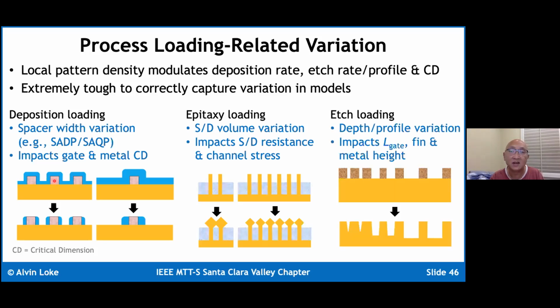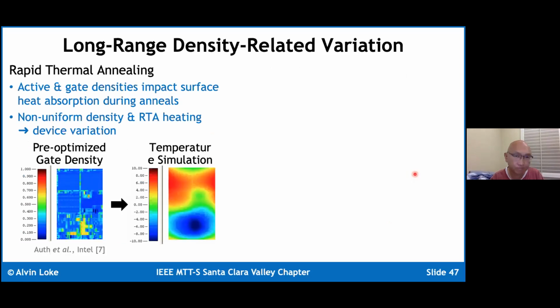And so you can also run into epitaxy loading effects depending on the number of fins you have, and etch loading effects where the etch depth depends on the spacing, the opening that you're trying to etch. All these effects need to be controlled with DRC. You also have long range density effects. For instance, rapid thermal anneal.